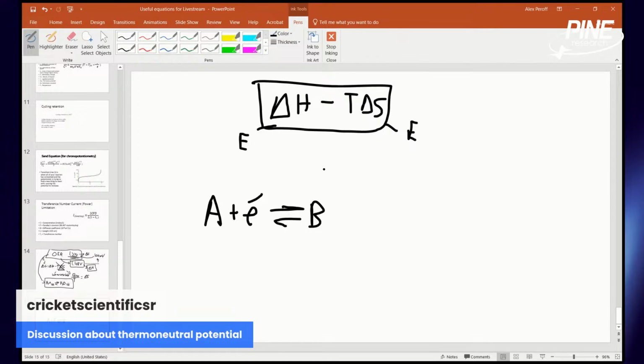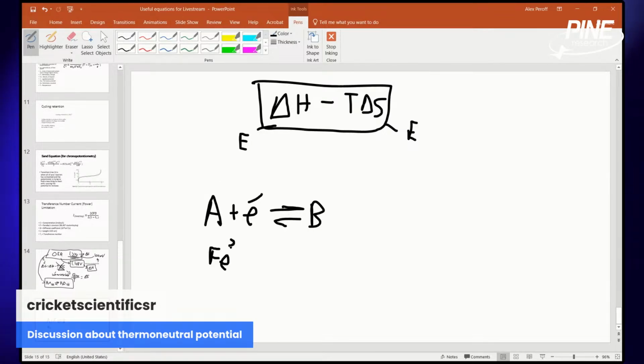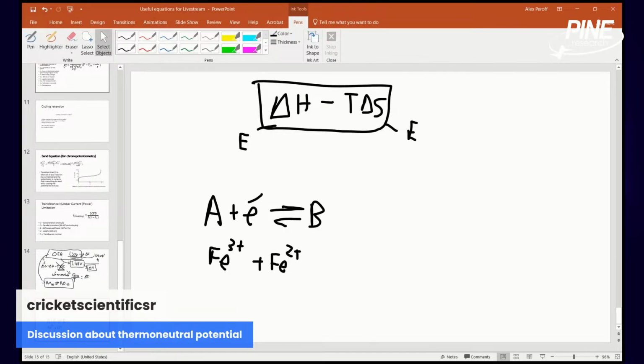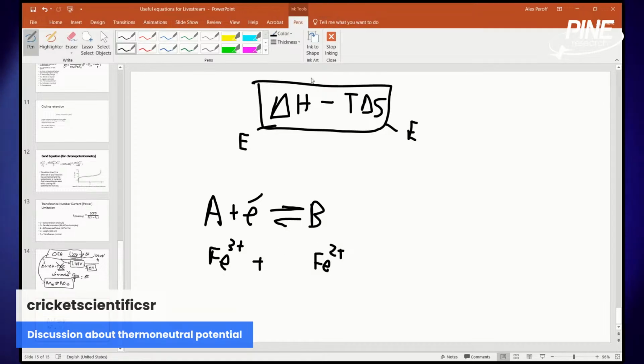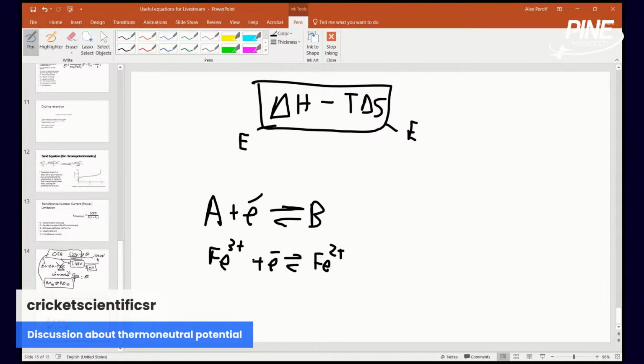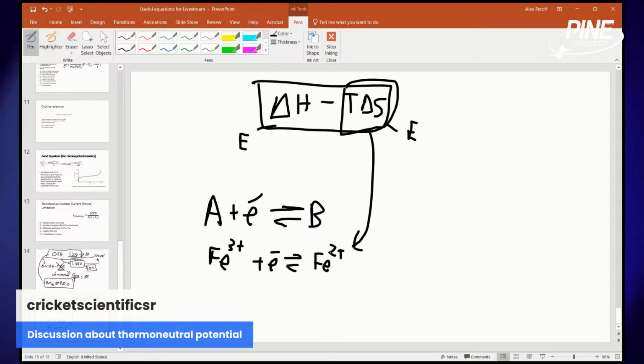The argument is that when you have things, or let's make it even more realistic, let's say we have iron 3 plus and an electron going to iron 2 plus. The entropy change between iron 3 plus and iron 2 plus is typically pretty small. It's definitely smaller than the entropy change associated with the oxygen evolution reaction, right? But I think there is still an entropy component to this reaction that creates an overpotential necessarily.